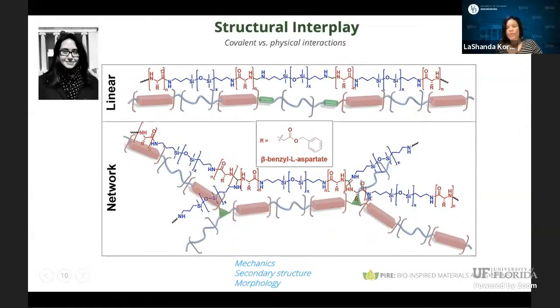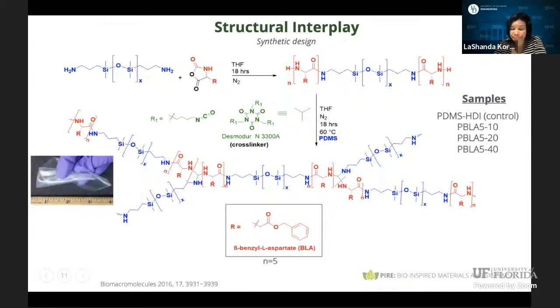So with this in mind, what we wanted to then think about is, can we now change the connectivity in these systems to be able to further control this hierarchy with the goal of really satisfying the space, much like spider silk. So we wanted to make a comparison with both linear systems and those made from a network. So still using PBLA as our system and PDMS, but now changing how we connect with the hard segment. So here, this is a synthetic scheme, but the real point is that we're using an HDI-based Desmodur crosslinker, so it's a trifunctional crosslinker, as our node points in these systems.